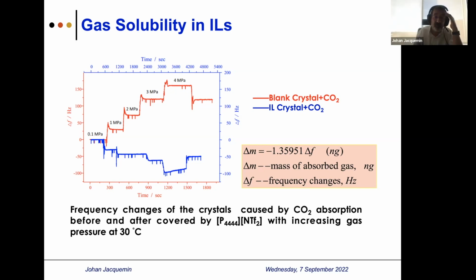And if we look at this example, why I picked this, because this data set is not very stable at very high pressure, and shows clearly a limitation of the technique. And of course, we repeated this many times, and we had to make the measurement longer. But we observed a drift, which was, from our perspective, due to the swelling effect on ionic liquids. But such a type of data, from my view, if you want to deal with gas solubility, must be reported to really truly evaluate data.